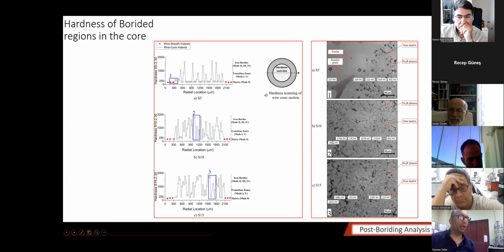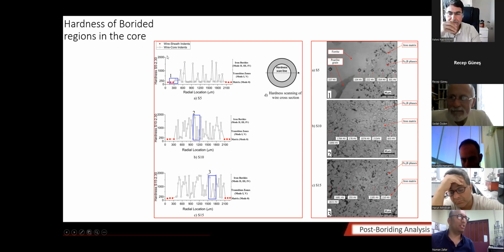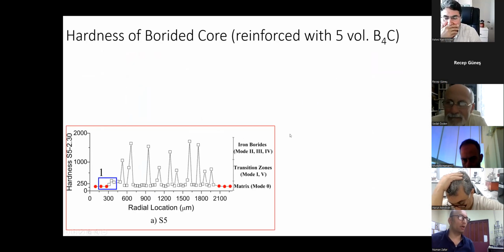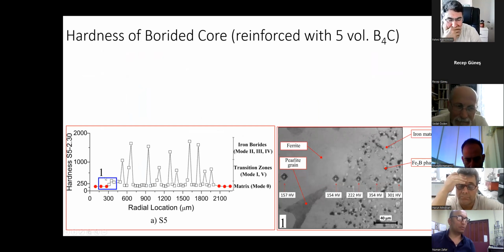These graphs are prepared to characterize and also to see whether we have actually succeeded in increasing the hardness of the material or not. So we have done a hardness scan line on the wire cross section of the S5, S10, and S15 specimens. These rectangles 1, 2, and 3 belong to the indentations shown here. For example, these red indentations are from the sheath, these two, and the remaining are from here. I will magnify them so that we can talk about this. Because a small region is borided in the S5 specimen, more indents belong to the matrix, and very few belong to the high hardness region.